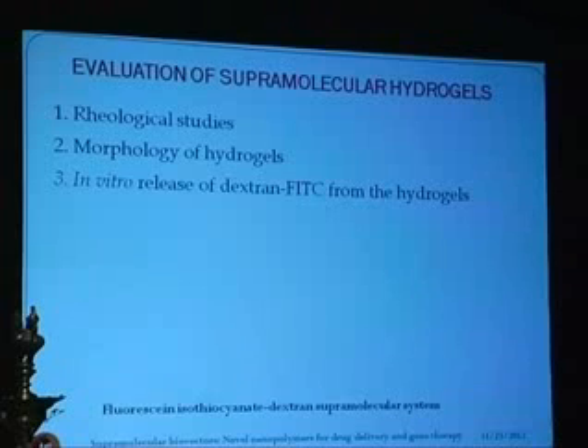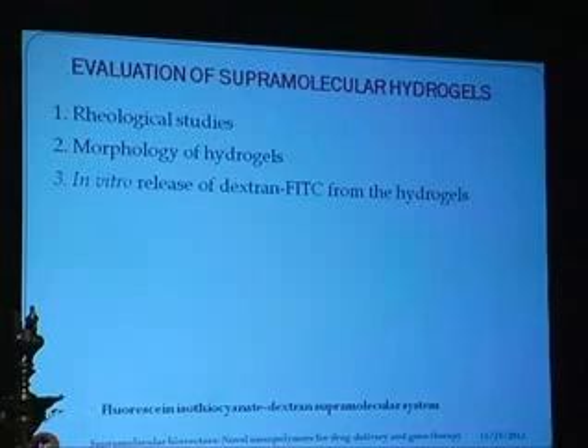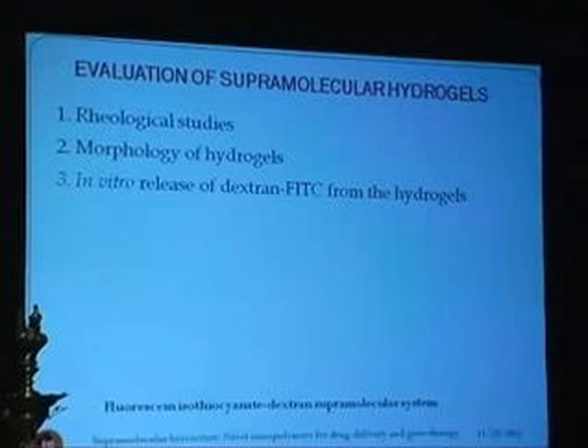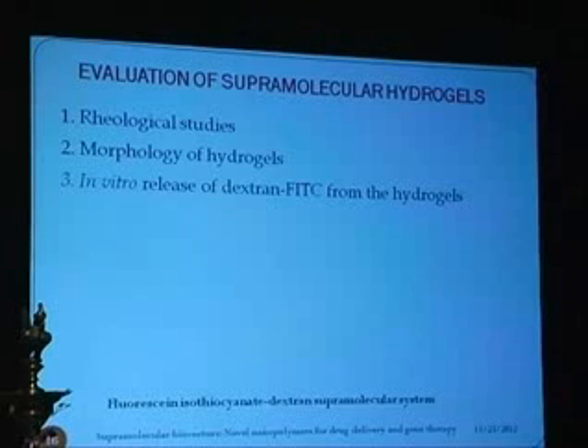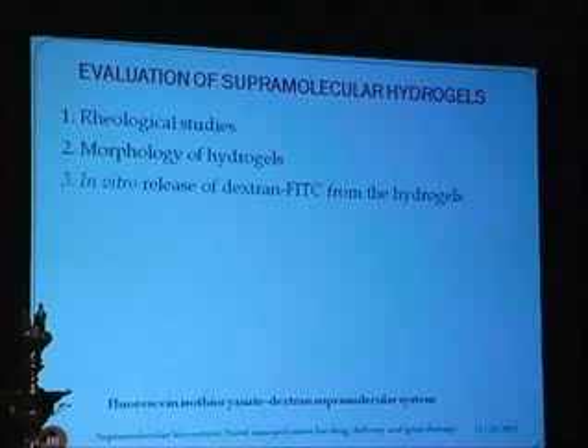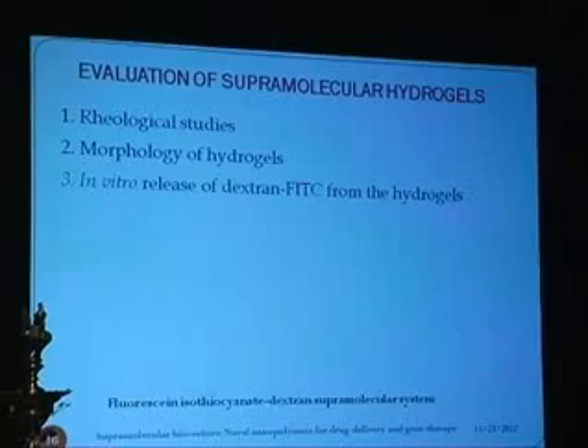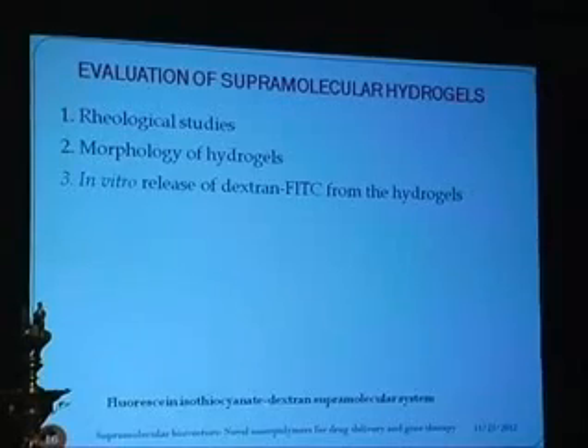After preparing or fabricating the supramolecular biovector or polymer, you have to evaluate or characterize it. Whatever supramolecular hydrogel you prefer, what should be the viscosity, whether you have done any rheological study or not, and how the viscosity changes. Sometimes you take low viscous supramolecules, but once you design a formulation, the viscosity immediately increases. What will happen? What should be the cause? Everything you have to perform, and you have to find out the requirement. Is there any polymorphic change after preparation, crystalline to amorphous? If it changes from crystalline to amorphous, the solubility also changes.